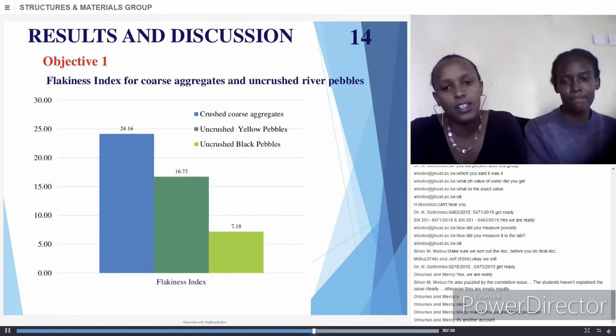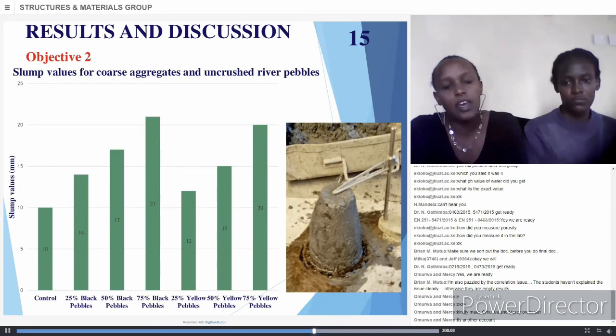The crushed coarse aggregates were the most flaky from our results, and black pebbles were less flaky, followed by the yellow pebbles. For workability, the mix with a higher amount of the river pebbles, that is black, was smoother with high packability and a high slump; as the quantity of the pebbles was reduced, the slump was reducing.